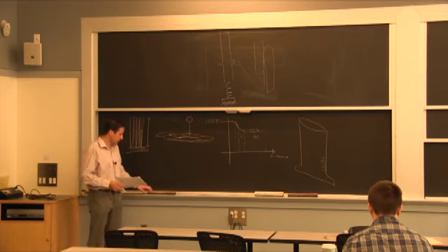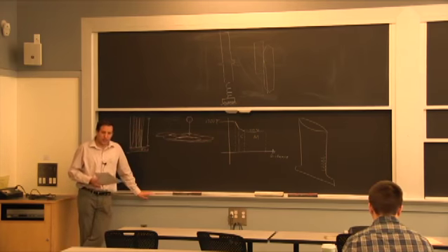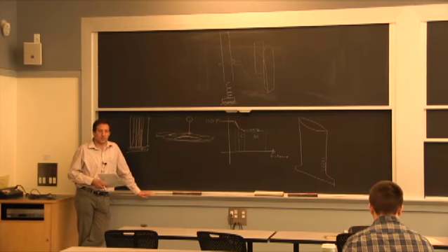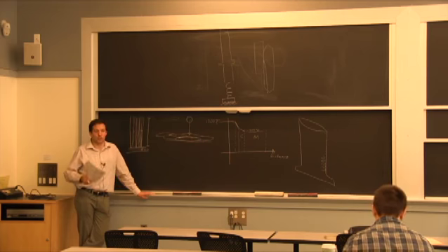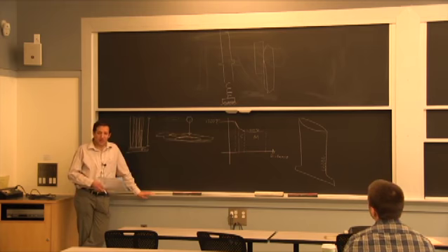The reason is, we talk about material selection, and sometimes you can use a material that you would not use otherwise just by coating it. If it's not all of it, it could be just part of it. So say you have to connect a piece of stainless steel to a piece of regular steel, and at the connection you may have a lot of moisture. You can coat your steel with zinc or stainless at that end and just get away from a galvanic effect in that area. I've done that before.